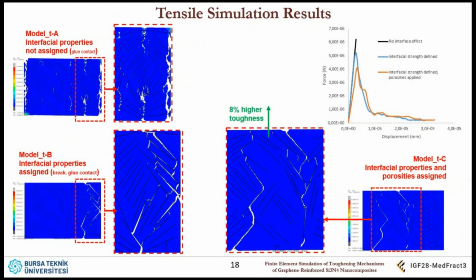And the findings, the results are like this. These are the zoomed in images. In the model with no interfacial property, like firm connection between the faces, you see the cracks are straight. In the other models, we see more realistic crack paths. But when we compare these two, this has got longer crack paths, therefore improved toughness. And these are the force displacement curves. So this one represents this with porosities of the cracks. And when there's no interface effect, this goes even higher. So no toughness there, just very little toughness.